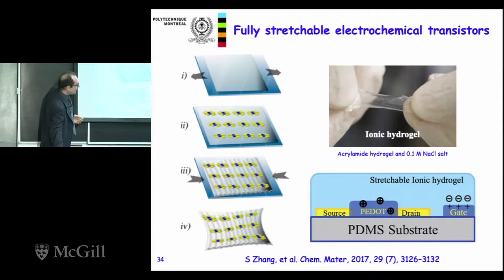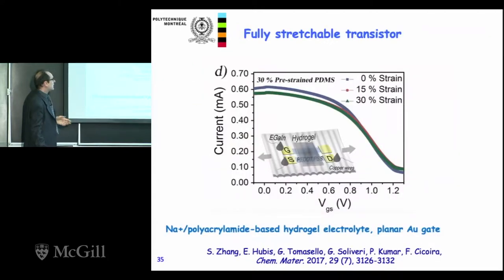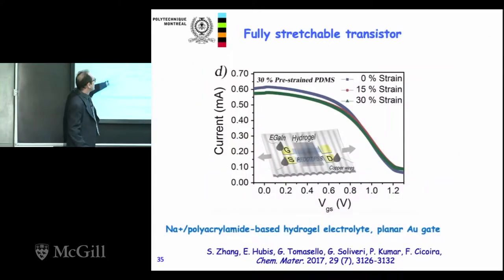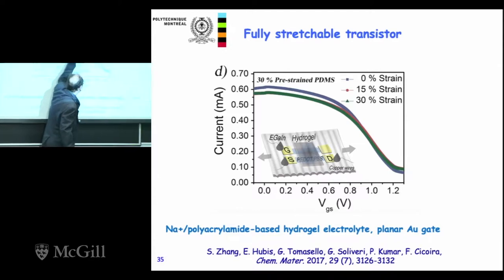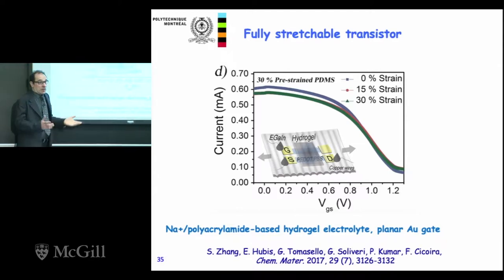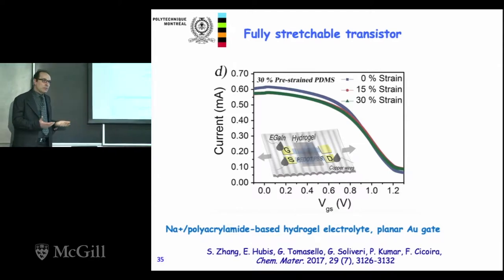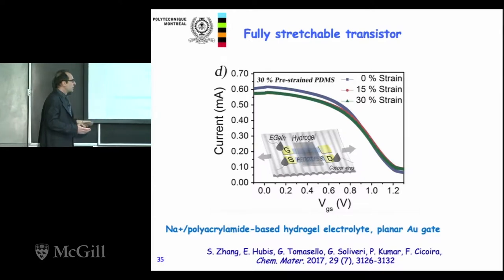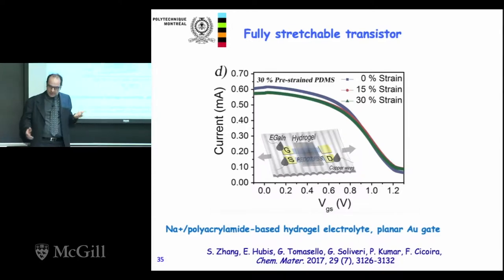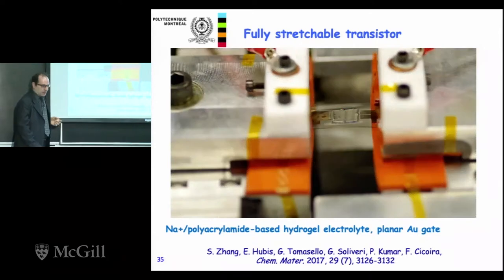And then we could make a device which is completely stretchable. And the characteristics are shown here. So you see here the characteristics at 0, 15%, and 30% strain. They are almost identical. So this shows you that these devices can be stretched up to 30% while keeping the same characteristics.